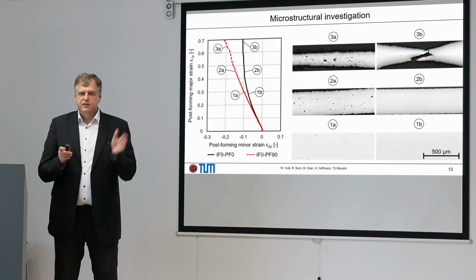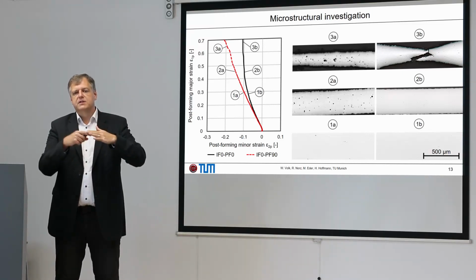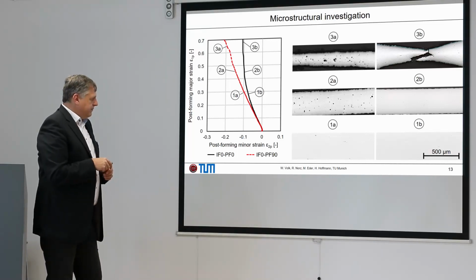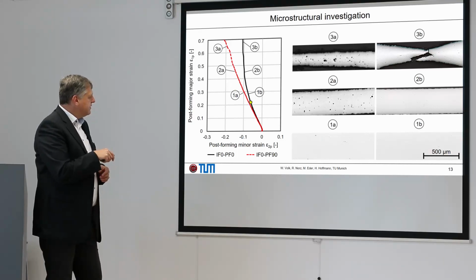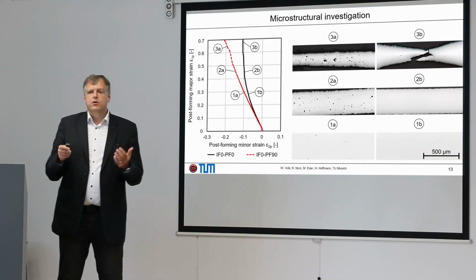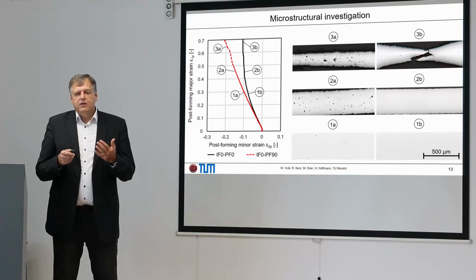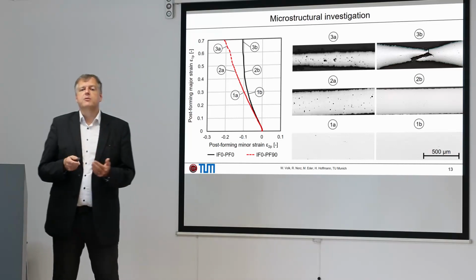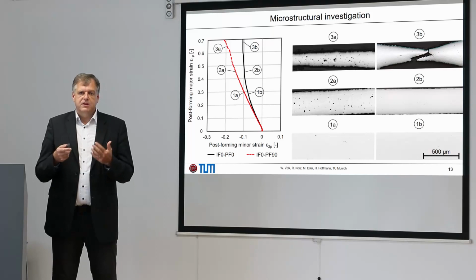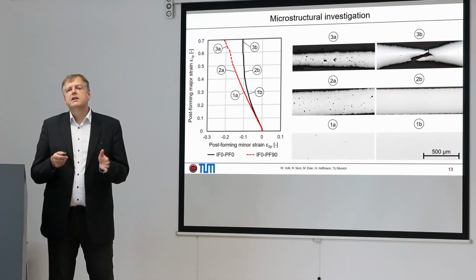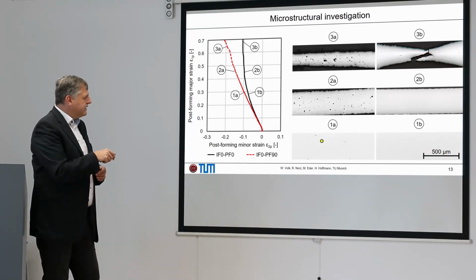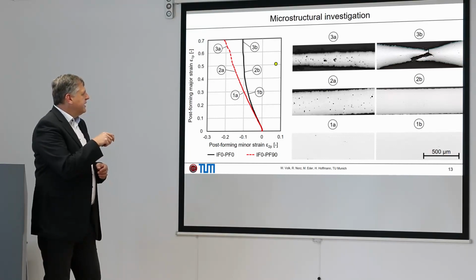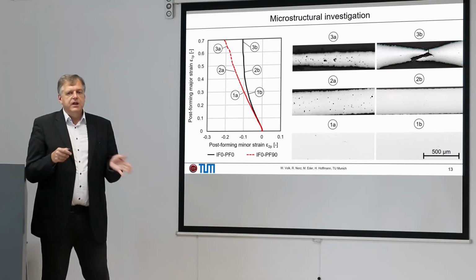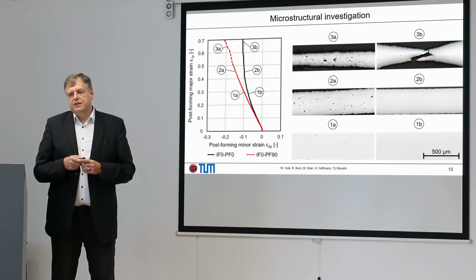But now have the look on the second curve. Again, only difference, 0 degrees preform and just turn around and then the second forming step in 90 degrees. What we see, direct after start of the second forming step, we have voids which occur. That means the start of microvoids is here not caused by a three-dimensional stress state, just due to the texture development based on the preforming step. And this, from our point of view, is the first time that we really can prove that this is an effect leading to different failure modes. Then we have the increase of this microvoiding and finally the fracture. And due to this enormous amount of voids, we don't have the skip into the plane strain behavior.